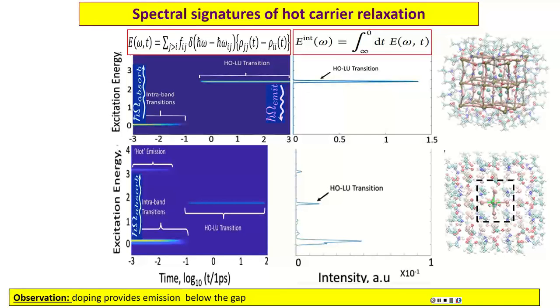Well, in this specific set of numerical experiments, the observations were a little against the original expectations. Substantial expectations were put on finding noticeable strong emission from the doped quantum dot. But it was found that undoped is much brighter. There is a specific protocol, quite easy, to assess the quantum yield of photoluminescence. You just take the fraction of radiative over radiative plus non-radiative processes. And for undoped, it was about 33%, and for doped, it was less than 1%. This is not what we want to have.